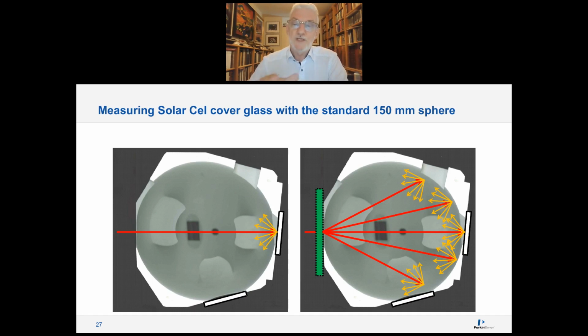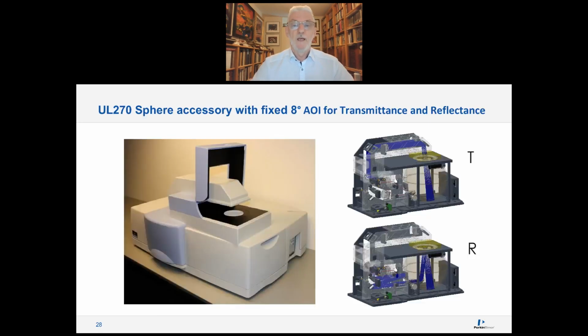Because normally they should be screened from the direct beam, the direct transmittance, not only from the sample, but also from the first hit on the wall. And you see that here, some of that is not exactly screened. So this is one of the reasons, actually I mentioned two, why you have a discrepancy in results.